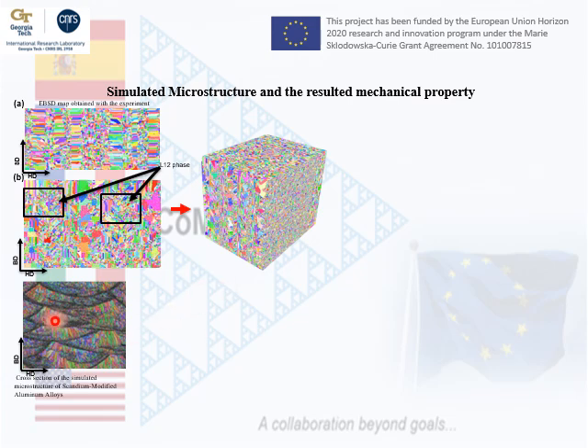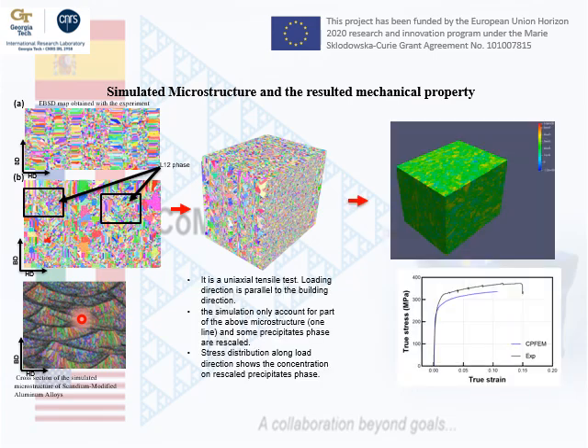So for that reason, we're simply simulating certain parts of the melt pool, right? Also, we are doing this simply because we need to transfer the three-dimensional information from the cellular automaton model to the crystal plasticity model, right? And the crystal plasticity model is also limited by memory, right? So for that reason, we cannot fully utilize all of the information from one model in the other. We need to make a simplification, and this simplification simply means that we need to utilize a smaller volume than the one that we can simulate in the cellular automaton, for example.